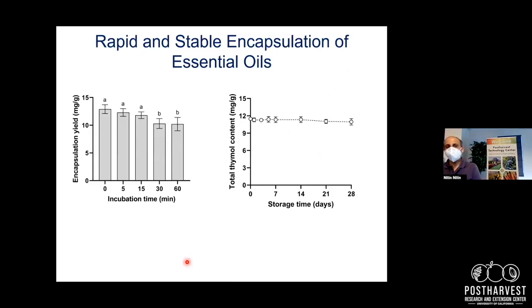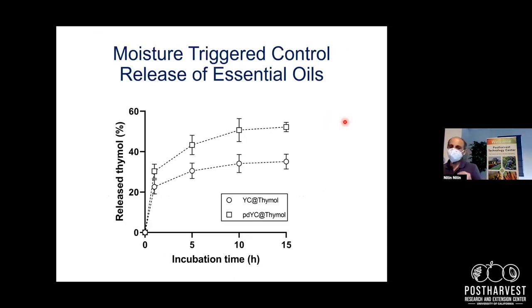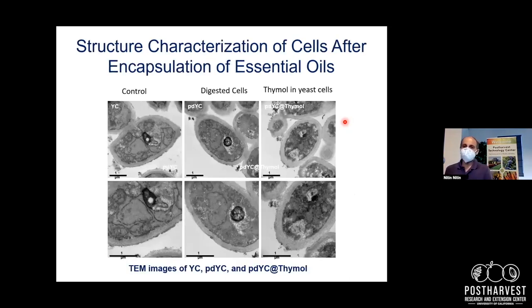One of the applications that we are working on in this area is to improve the stability of essential oils and some of the other ingredients over an extended period of time. These essential oils are one of the categories of volatiles that have been of significant interest to the produce industry in terms of both antimicrobial properties as well as the ethylene suppression properties of some of the essential oils. So we can get very high yield. We can develop formulations which are stable for an extended period of time. When exposed to moisture, we can design their release profiles. We can design fast releasing, slow releasing materials from different compositions of the yeast itself without changing significantly. These are some of the images of the yeast cells with the encapsulated essential oil in them.